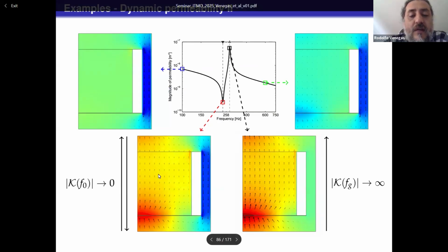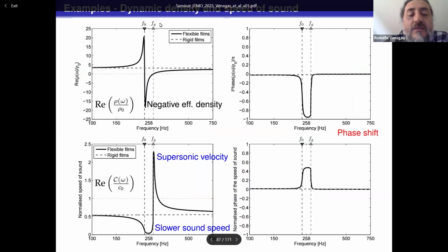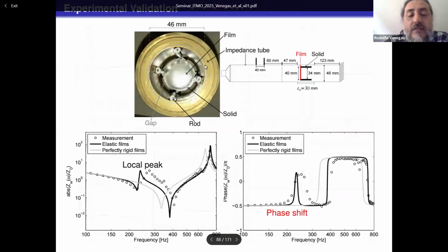So this is what happens at this point. The flow is very high here and goes in this direction due to the vibration, and around this gap it goes in the other direction. So when we take the average, it goes to zero in practice, and that explains the minimum. And at the maximum, the flow is pretty much driven by the vibration of the plates. So in between these two characteristic frequencies, we have a negative effective density. Above this resonance frequency, supersonic velocity and a phase shift. And this is the experimental validation where we can see that there is a phase shift related to the resonances of these small plates.